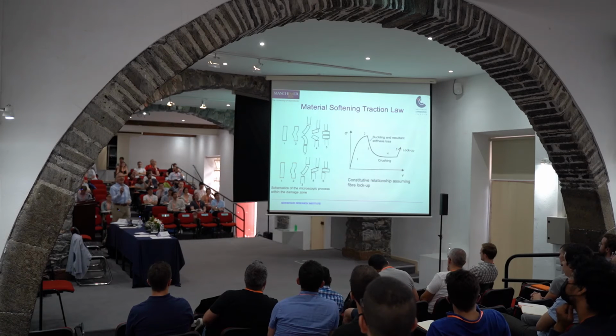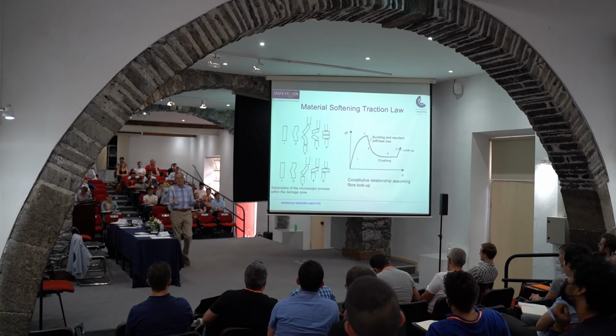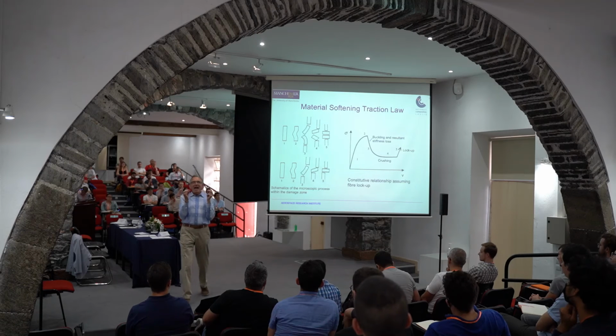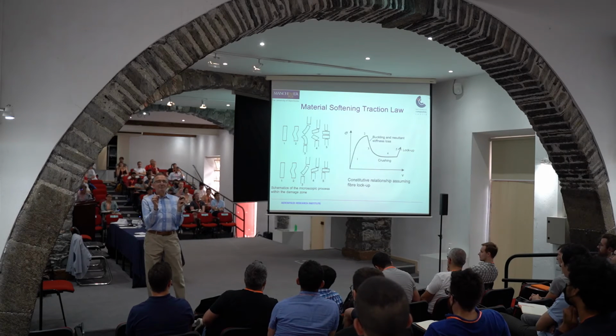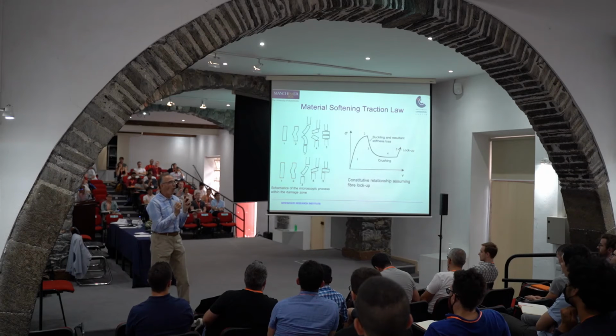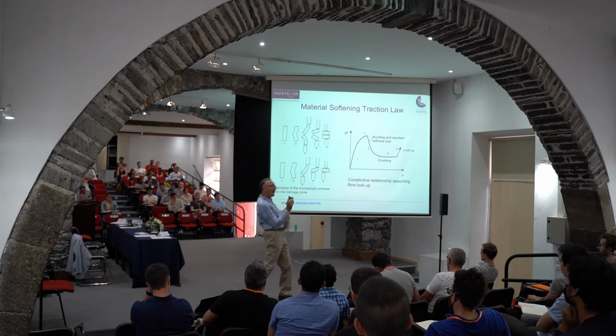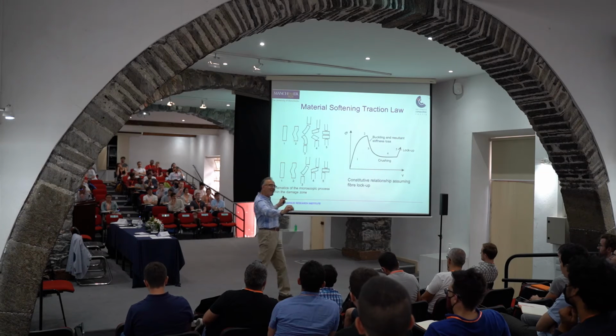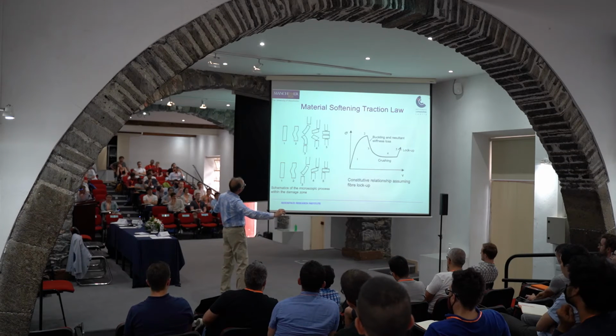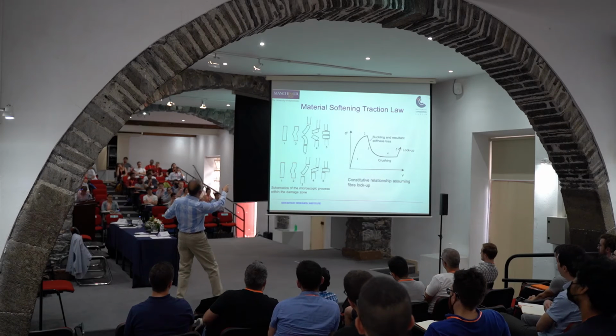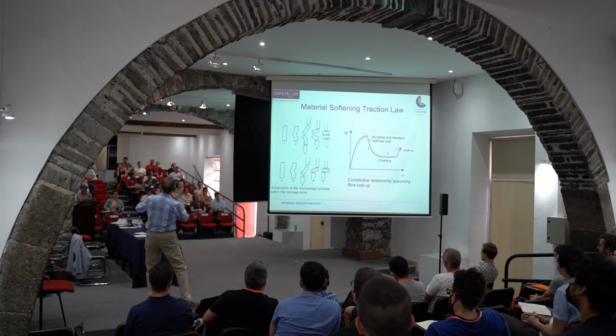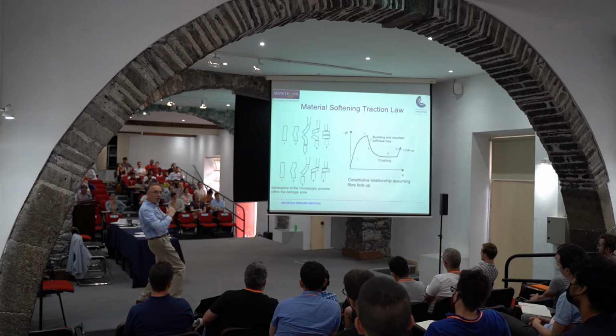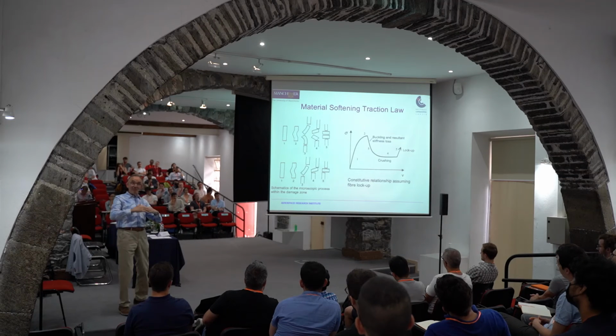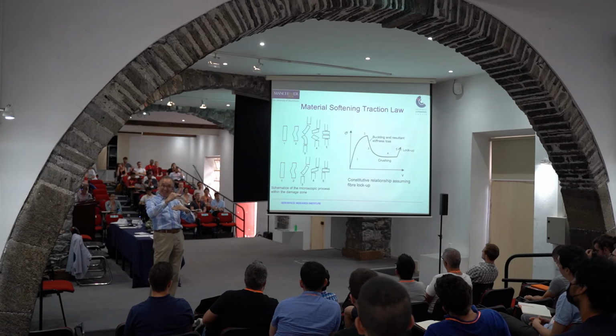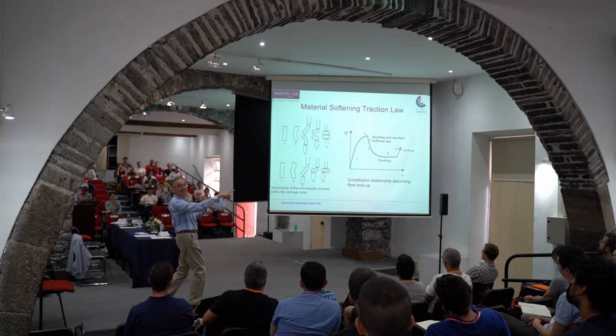And here, of course, this is a fracture mechanics course, isn't it? So I'm trying now to calculate how much energy is absorbed by the fiber microbuckle, or how much resistance the fiber microbuckle provides to the propagation of the damage. Okay? So the fiber bends, it breaks, the fragments rotate, they lock. If they lock, of course, they provide more resistance to the applied load. And then if you look at the local stress displacement curve, it looks like this.